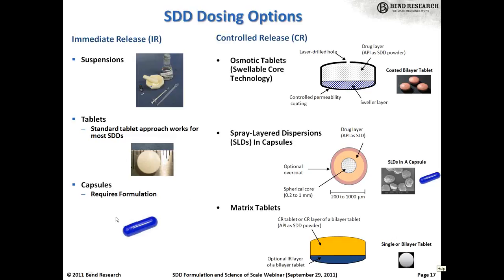They can be placed in capsules as well, although I would sound a bit of a note of caution there: when placing them in capsules, it's oftentimes necessary to do some formulation to provide good disintegration and dissolution and avoid gelling and slow release from the capsule. So it's not always a great idea to just shove the SDD straight into a capsule and dose it. So that's certainly something you want to look at if you go that approach.